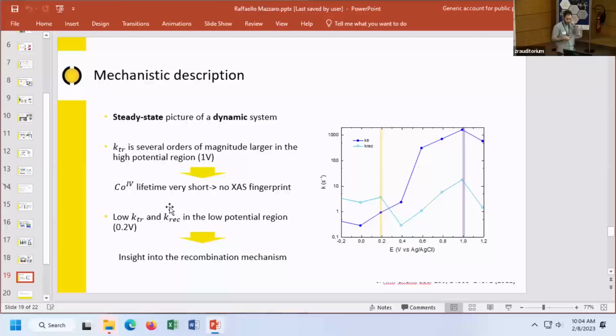Now, to understand how that works, we try to get a mechanistic description by comparing with the electrochemical data we have, and in particular we looked at the rate constants for the transfer and recombination mechanisms. We can recognize that in our experiments, we're working in two different regimes. One where we have very fast charge transfer at the interface, which means that as we are looking at the steady state picture of our system, we're not looking at any variation in our catalyst oxidation state, as all the holes transferred to the catalyst are immediately transferred to the solution. So in this case, we are not expecting to see anything, and that is actually what we saw. While in this case, we're working in a range where both transfer and recombination rates are much lower.